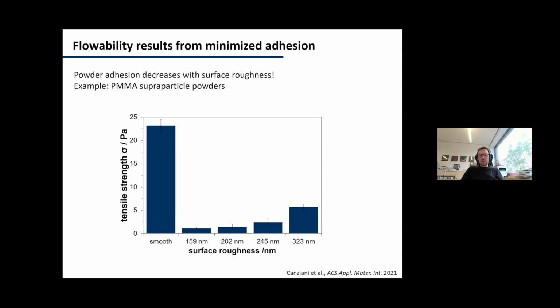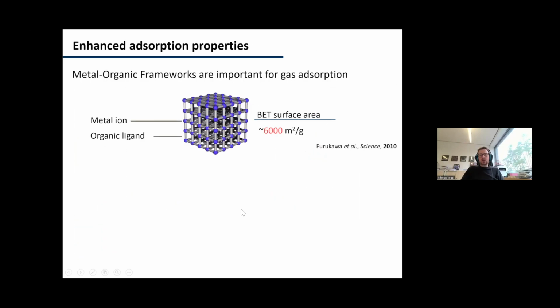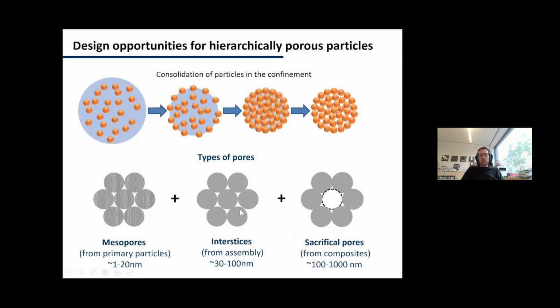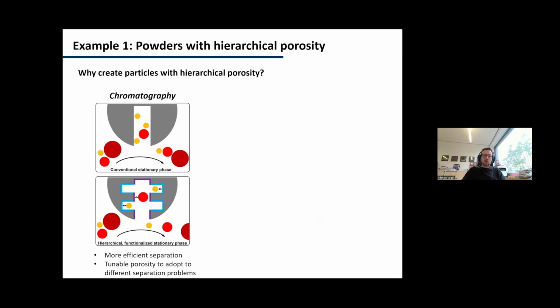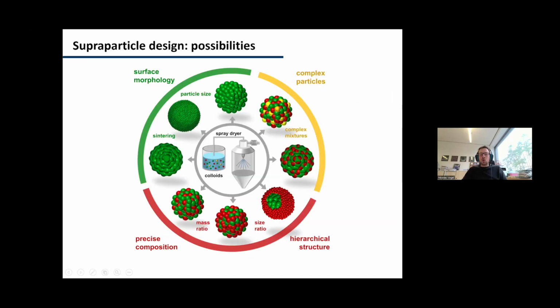Yeah, so in this case, if I go back to how we make the supraparticles, then typically normal powders are either formed by comminution, so by grinding particles, or by precipitation. And that means that you typically, sorry, that's not what I wanted to show. It's this one here. So you typically only have a single polymer species. So you would be somewhere here. And whenever you want to incorporate something functional, you then need to mix it physically. And that means that you don't have a very homogeneous distribution of multiple particles. And again, you risk that the flowability is not so good.